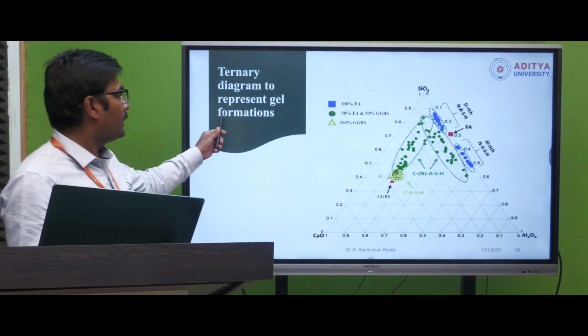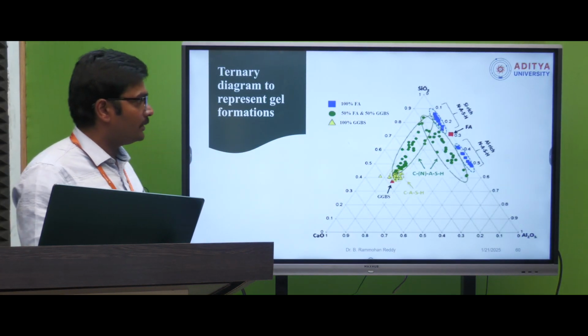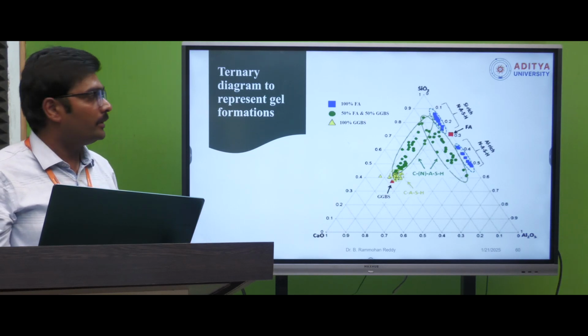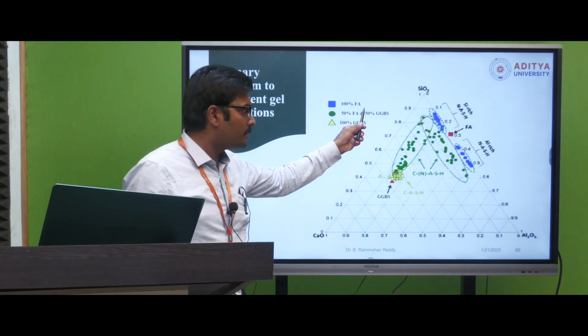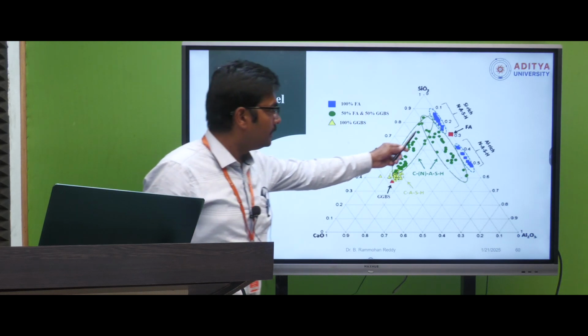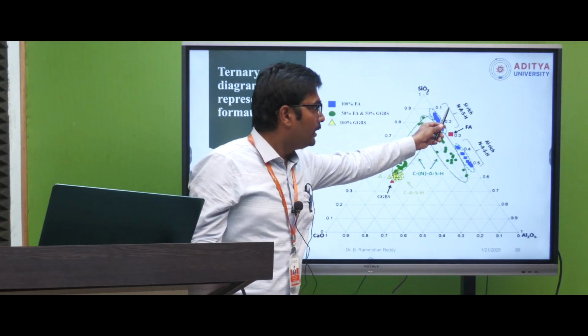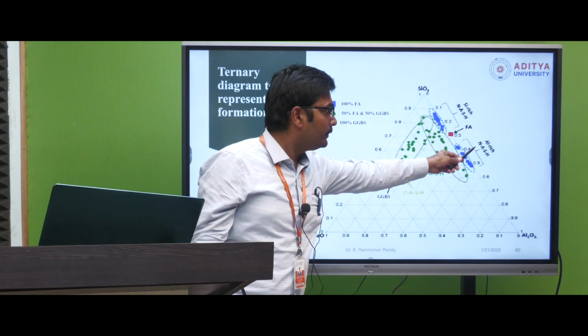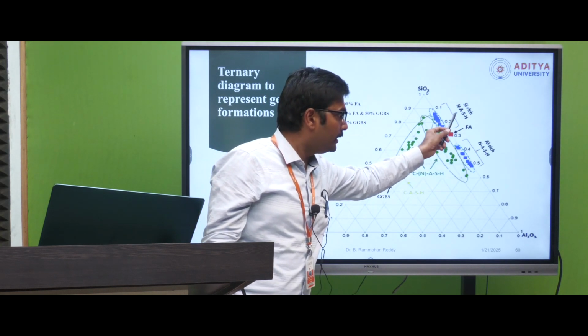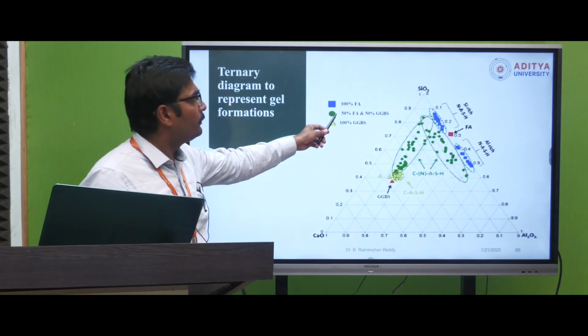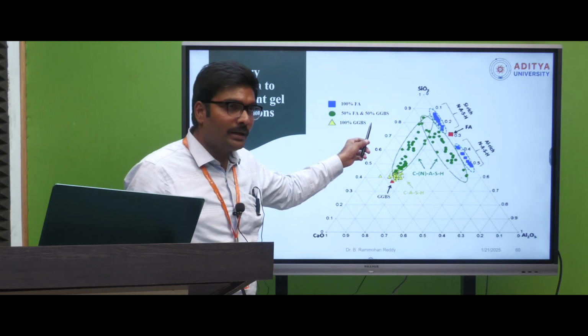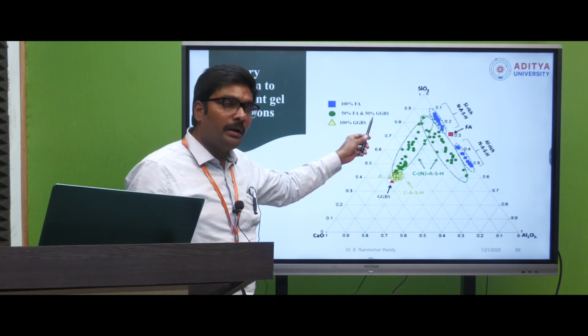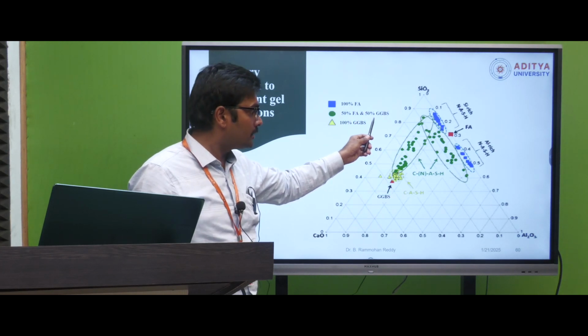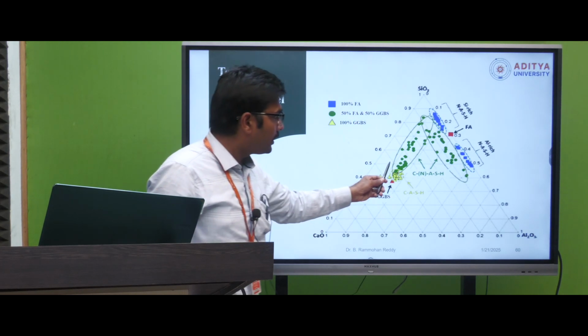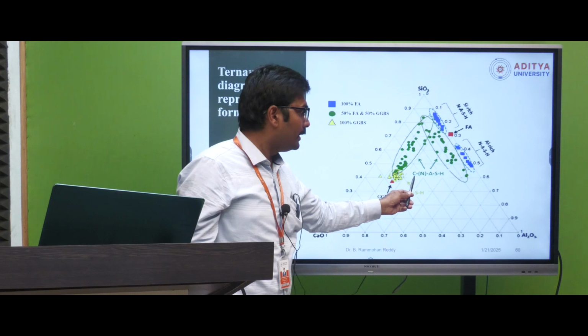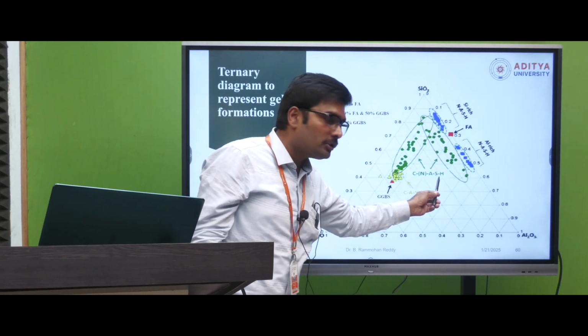And the ternary diagram will represent the gel formations based upon the industrial byproducts that we are choosing. So if you are using 100% fly ash, you can see this blue indication, N-A-S-H. If it is silica rich and alumina rich, the N-A-S-H gels will form. If you are using 50% fly ash and 50% GGBS, meaning silica, alumina and calcium rich materials, then you can see this green color. So either C-A-S-H or N-A-S-H will form